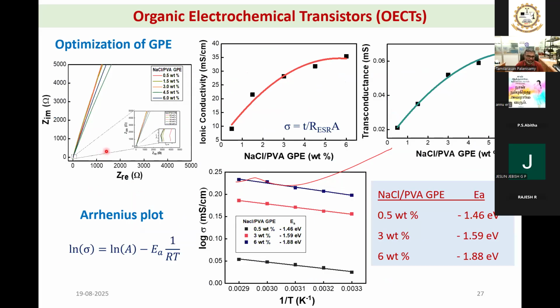We have made a NaCl PVA gel polymer electrolyte with different NaCl loading. And you can see when I change the NaCl concentration, the ionic conductivity gradually changes, but it is getting into some saturation. And the transconductance, when I use this electrolyte in the OECT as a dielectric, I will get the transconductance. The transconductance is also gradually increasing, going all the way to 6 wt%.